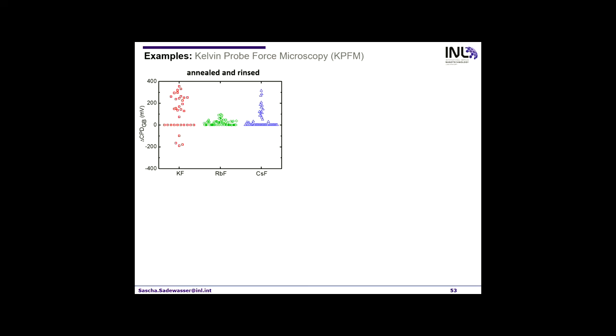That's quite sizable. And in this study, we extracted 20 to 60 profiles in each of the samples, and we plot then the CPD difference for all of these 3 different treatments. So overall in this study, we analyzed more than 240 grain boundaries, which was a lot of work. And what we find is, for potassium treated, we see a lot of grain boundaries that do not change at all. So this is why we use the topography to identify the grain boundaries, because if we only would use the CPD image, we would not see, of course, if there's a grain boundary that doesn't change, it would be invisible. So we have this part, then we have a few grain boundaries that show downward change in potential, and a lot of them upward. For the rubidium one, we only see upward and neutral ones, no change, but the change is also much smaller. And then for the cesium, again, we see some more with larger changes, but again, no negative ones.